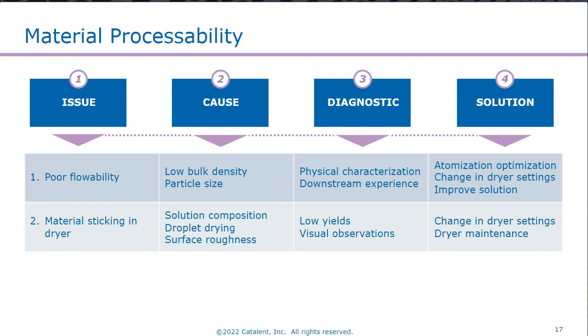Another common set of issues is material processability. Spray-dried powders are known in the industry to have issues with flowability, and that product attribute of the spray-dried intermediate needs to be controlled and troubleshot during scale-up. This poor flowability comes from the generally low bulk density of these materials and the small particle size. The diagnostic of this is physical characterization and then downstream experience.